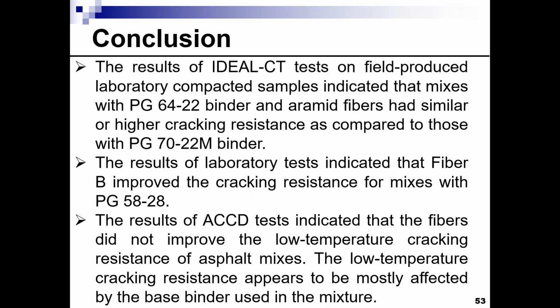One of the things that we have also found is that the fibers did not really improve the low temperature cracking of the asphalt mixes. And again, this is based on the ACCD, so it's based on laboratory testing. This is not based on the field performance. And as I said before, it seems that the low temperature is affected by the base binder. So if you're using a PG 64-22 or a PG 58-28, the 58-28, because it has a lower end grade, is expected to improve the low temperature.